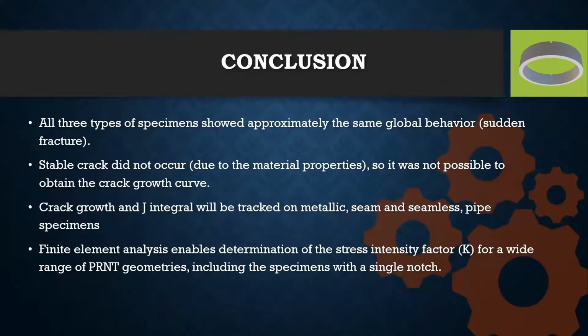And the conclusion. All three geometries of the specimen exhibited similar behavior without significant plastic deformation prior to sudden fracture. All three types of specimens showed approximately the same behavior, but without the possibility of obtaining a crack growth curve due to the properties of the material.